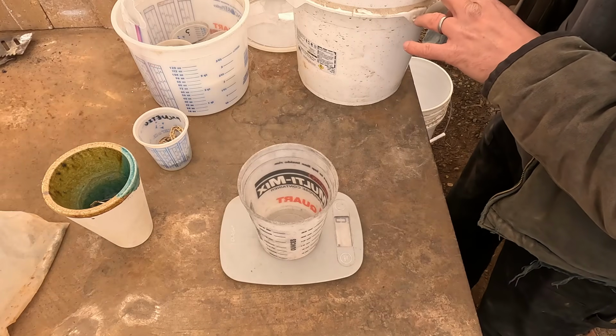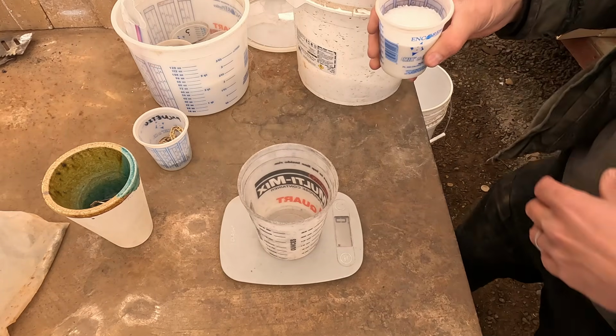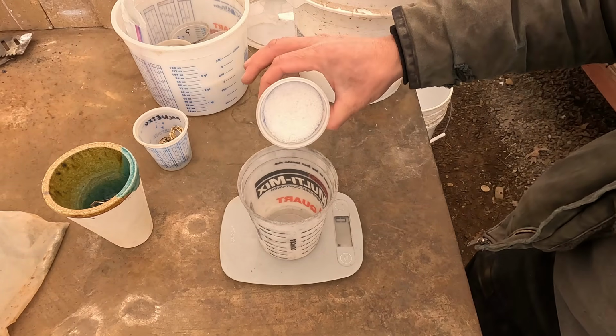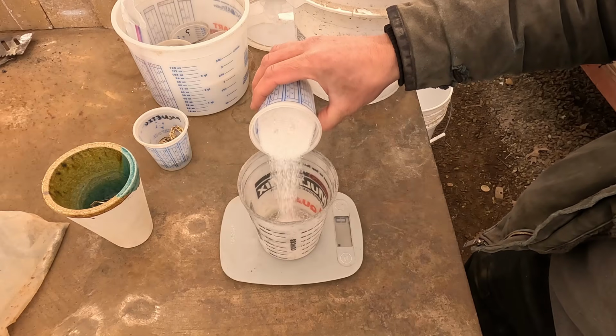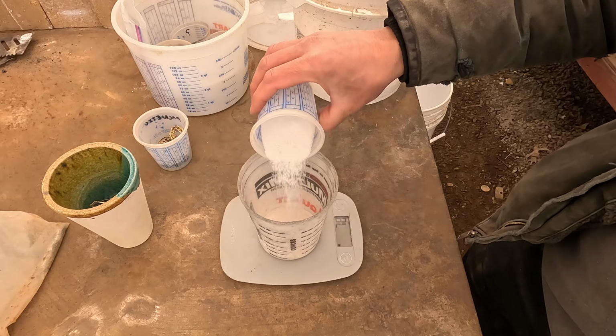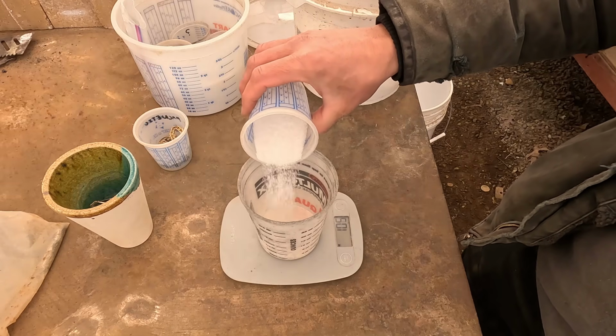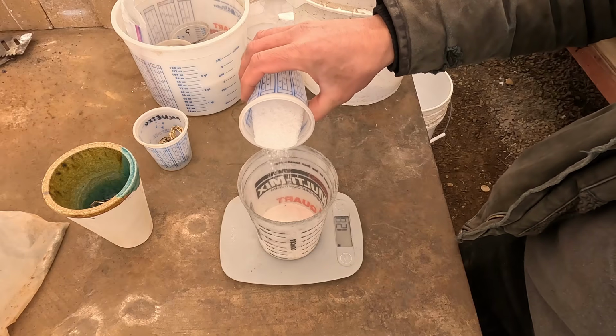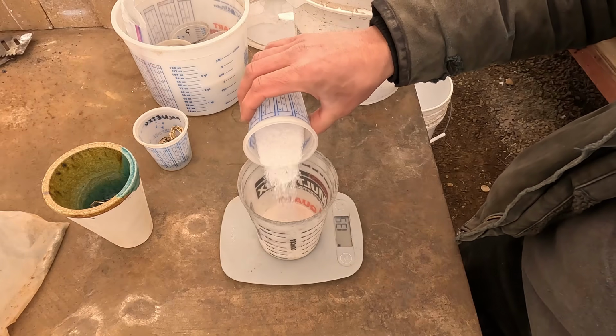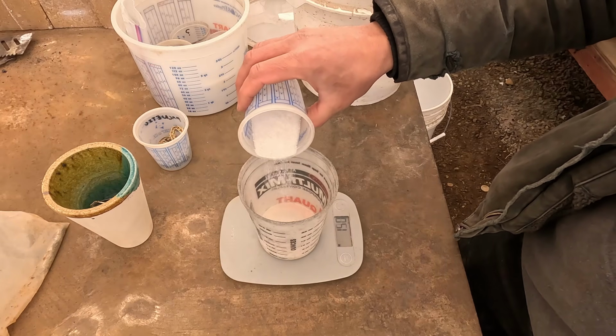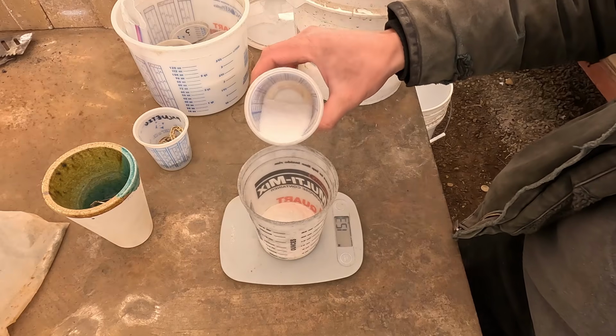So now for our flux. This is a pre-mixed flux. It's about 65% borax, 20% potassium nitrate, which is going to be our oxidizer. That's going to help eat up all the copper, zinc, and iron. And the rest is a little bit of silica and soda ash.